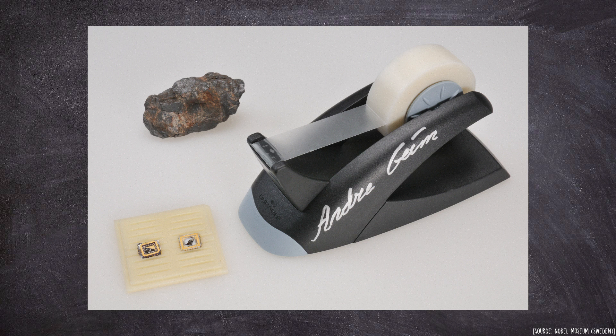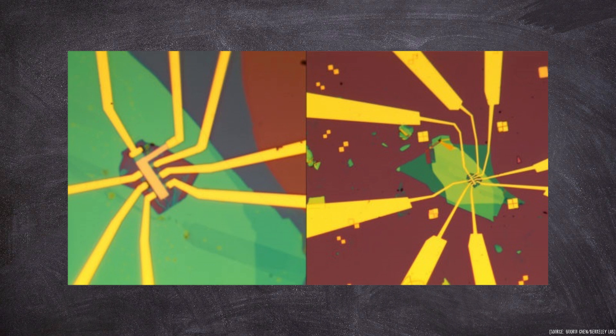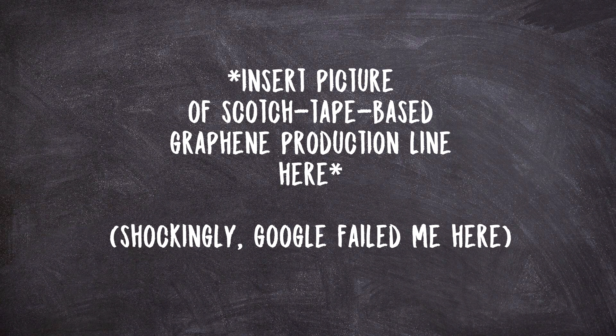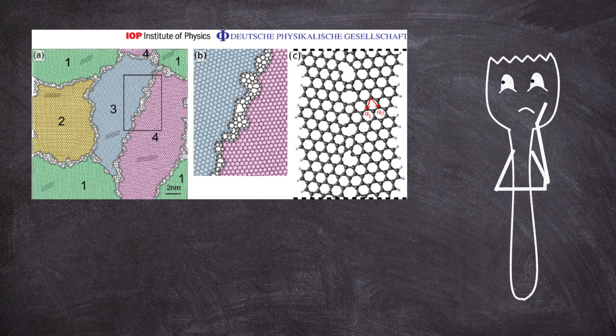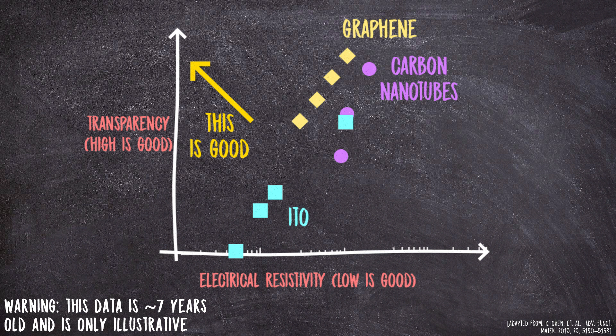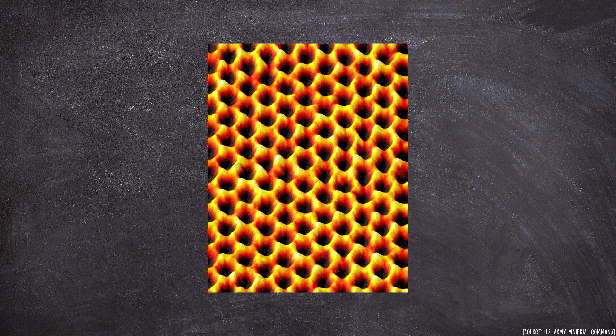In fact when we make graphene devices in research labs we literally use something called the scotch tape method where we take scotch tape to some pencil lead, peel it off, and search the tape with a really fancy microscope for a single high quality single atom layer thick flake, and then we just build our device right there onto it. This works for research devices but it's obviously not a viable option for consumer mass production. Except — here's the thing — this particular application, graphene as a transparent contact, is probably the most forgiving in terms of graphene's many many problems. Because even a very very crappy graphene film would be equal or better than what we already have on the table. I mean a TCO is a transparent conductor — it's an okay conductor but not a great one. Even swiss cheese graphene could probably beat that, and pencil lead is way cheaper than silver.